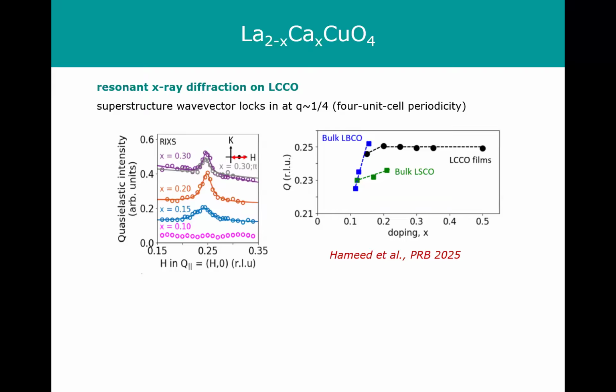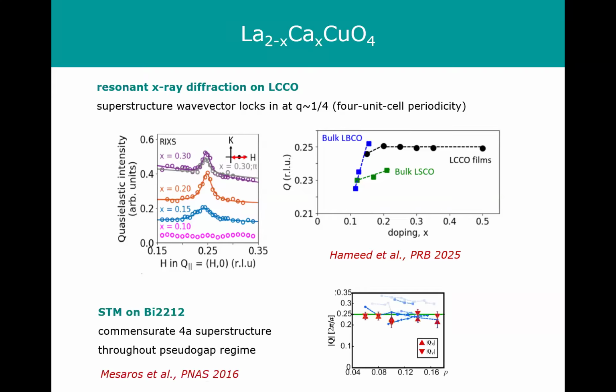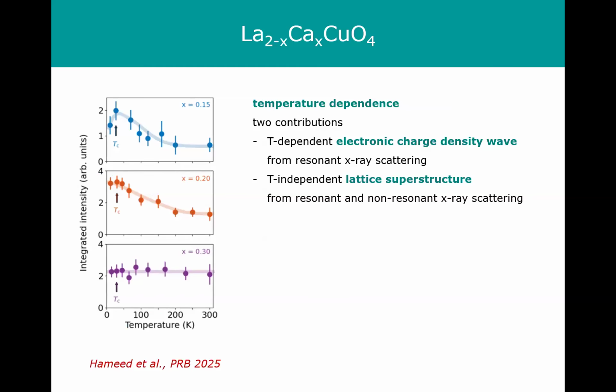So this is not unheard of. This is data from Seamus Davis's group on bismuth 2212 from STM. And they also found a 4 unit cell period superstructure over a wide range of doping levels. And there are other systems in which this kind of lock-in has also been observed. Now to see what the origin of this superstructure really is, we also did temperature-dependent measurements.